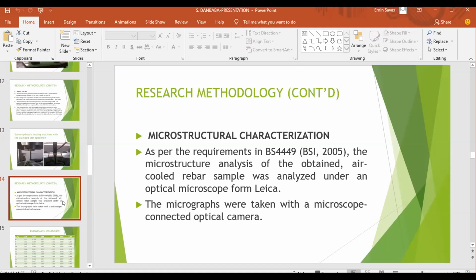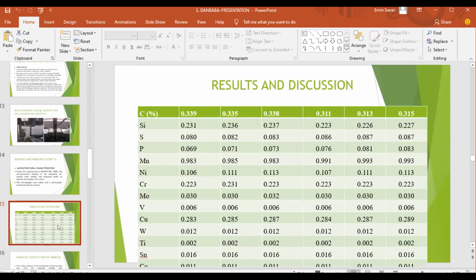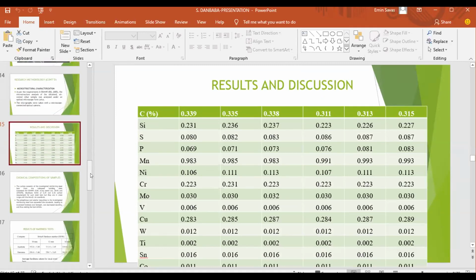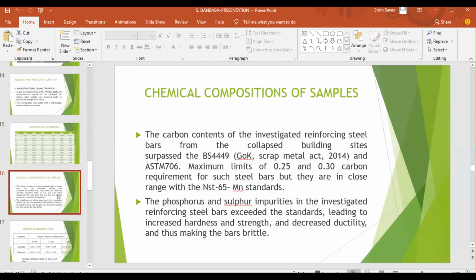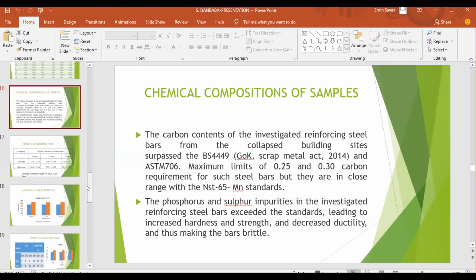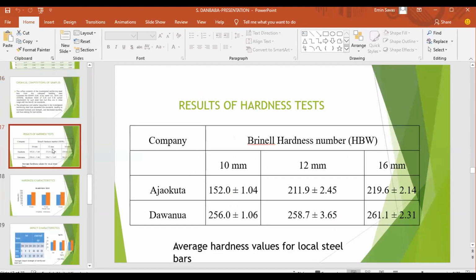The microstructures were, as expected, primarily a ferritic matrix with a pearlite distribution. The chemical analysis, these are in percentages. It starts with carbon, and all the elements in the samples were found as in the table. And the carbon contents of the investigated steel bars from the collapsed buildings were also checked. The two undesirable impurities, phosphorus and sulfur, were also checked. And it was found that carbon contents were above the contents mentioned in the standards.